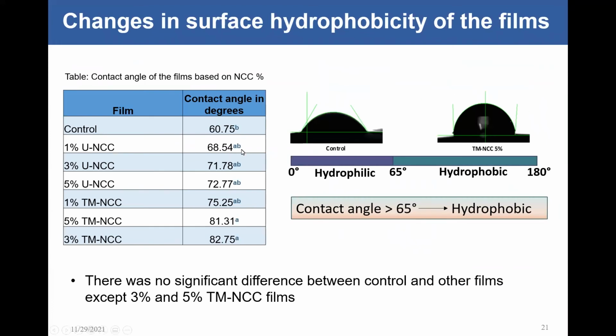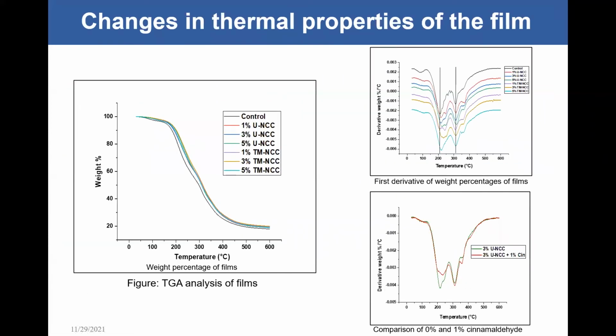We did manage to improve the surface hydrophobicity of the films with the addition of nanomaterials, as you can see in here, because we measured it through the contact angle. This is something that's very important when it comes to packaging film. So having that better hydrophobicity will help in better water barrier properties.